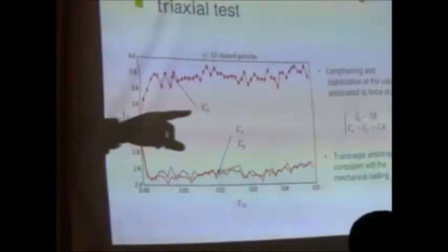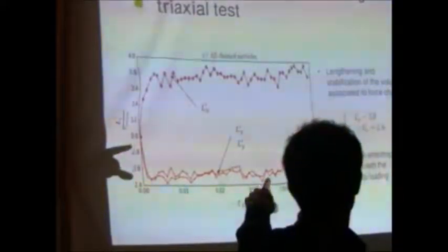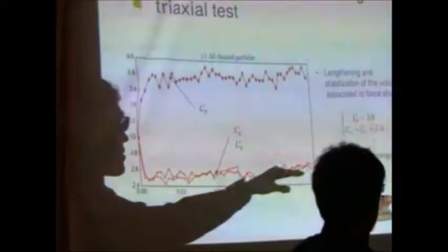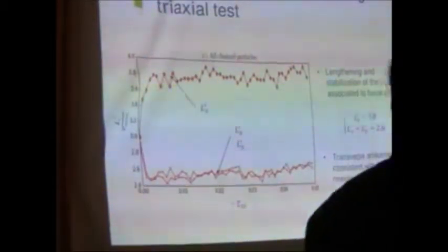And if you plot the evolution of these 3 length scale parameters with respect to the level of axial strain, then you see that the horizontal parameters remain mostly constant with a very small distance of autocorrelation. So this means that your structure is not very well correlated in the horizontal direction.